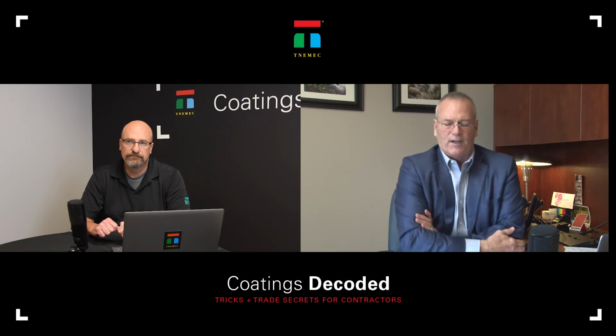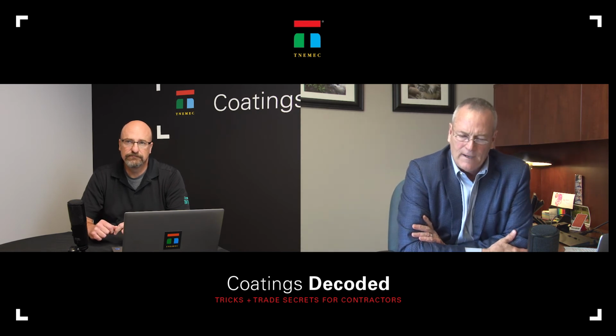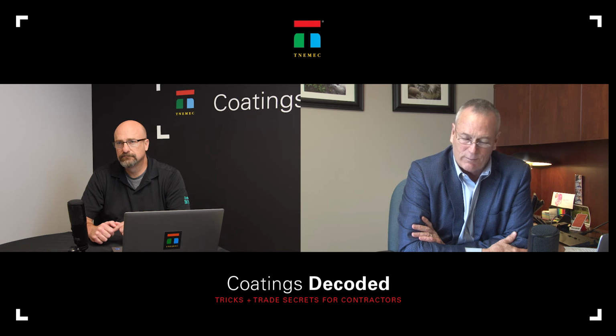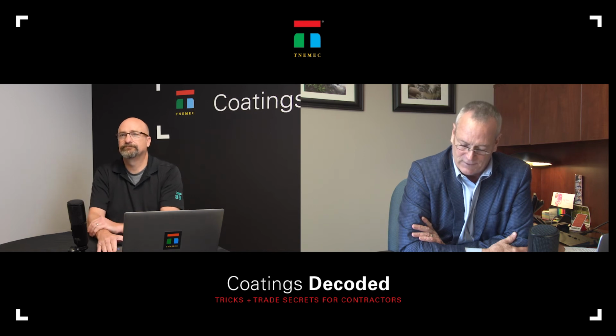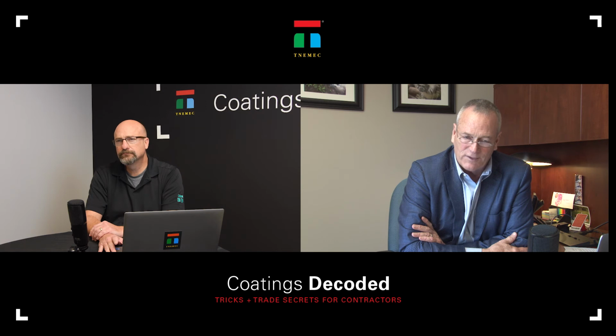Yeah, let's talk about the application properties. The inorganic zincs are a little difficult to apply. The surface preparation has to be just right. The application technique has to be perfect. They tend to be a little porous, so they can be difficult to top coat. Top coating, even top coating with itself, can be difficult. The organic zinc-rich primers are much easier to apply, and they have dry fall properties in many cases, and they'll have relatively short recoat times or dry times for top coating, which is a real advantage for shop application. And then top coating a hot dip galvanized product can be very risky.